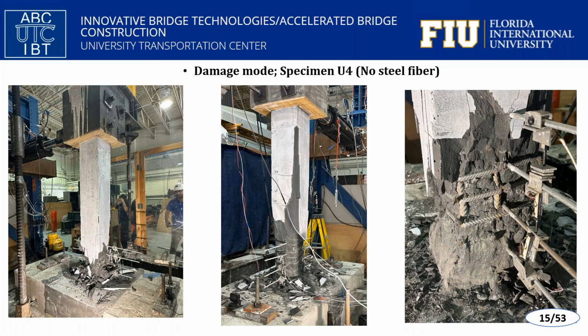Here you can see the crack modes for the specimen without steel fiber. Cracks propagate rapidly, with horizontal and diagonal cracks forming early and widening significantly. Severe spalling and extensive crushing of concrete occurred, leading to rapid loss of load-bearing capacity. We had to stop the test at 5-inch lateral displacement. Cover crushing occurred at early stage of loading. The absence of steel fiber results in poor energy dissipation and brittle behavior.